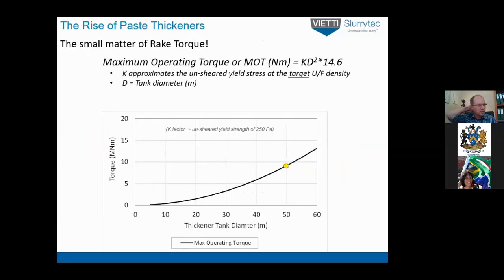Now it becomes quite interesting, because the way the size of a gearbox for a particular application is conventionally designed in the industry is using a very simple equation. It's important to remember that these calculations were derived in the days of conventional and high rate thickening, where the slurry generated tended to be a non-Newtonian fluid. It didn't have too much yield stress, or if it did, it was pretty low. So the calculation states that the maximum operating torque is defined by K, which is really an empirical number developed by the early thickener guys, times the diameter squared of the tank, times a factor which brings it to SI units.